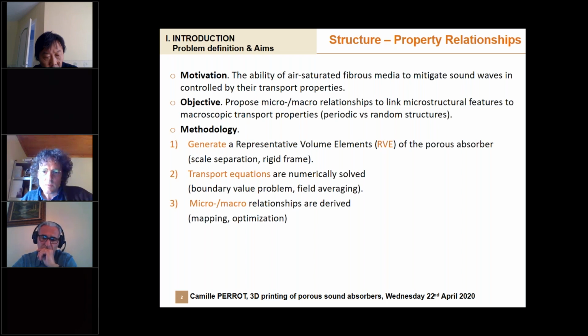So basically, one of the methodologies which has been greatly used in the field is to generate a representative volume element of the porous media, the porous microstructure, assuming a scale separation, which means that the wavelengths for audible frequencies are greater when compared to the sample scale, and also when compared to the characteristic scale of the microstructure, basically a typical pore size. Another assumption, which doesn't have to be firmly respected, is the rigid frame assumption.